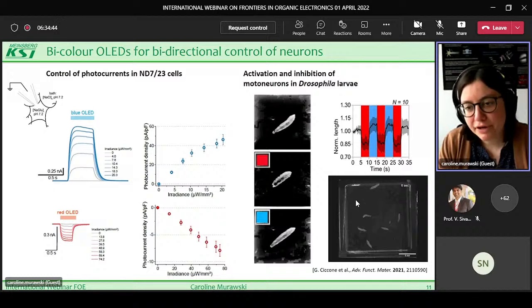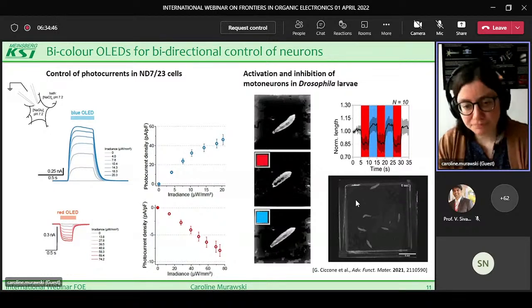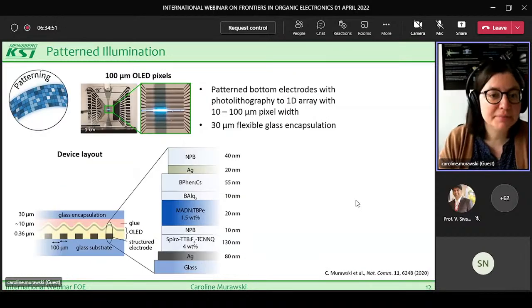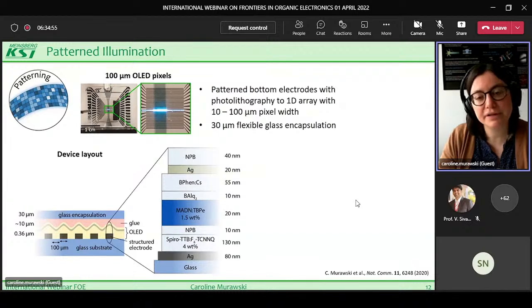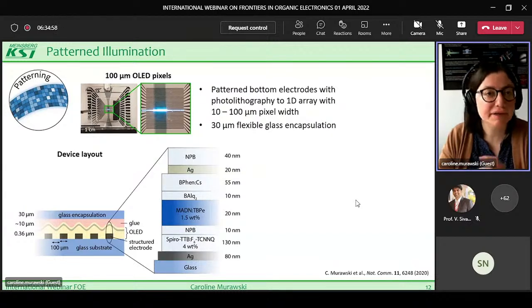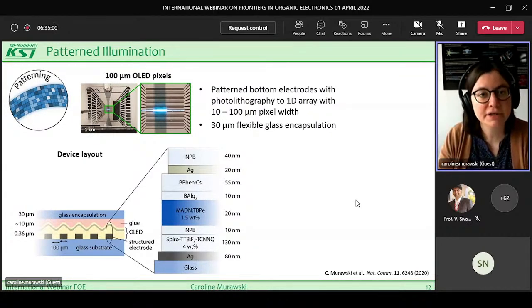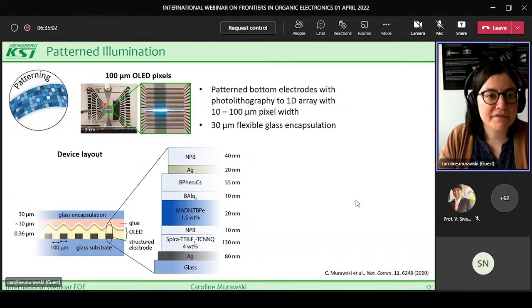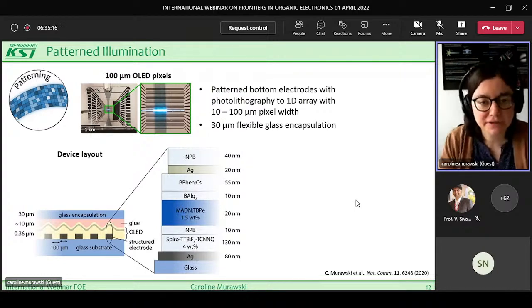Okay, so far I've always just shown you examples of using OLEDs that have a pretty large area, but we are also looking at patterning the devices to smaller area in order to stimulate cells with higher specificity. And for this, we've structured OLEDs by patterning the bottom electrode into such a one-dimensional array. So each of these little stripes can have a width between 10 and 100 micrometer, depending on the system that we use.